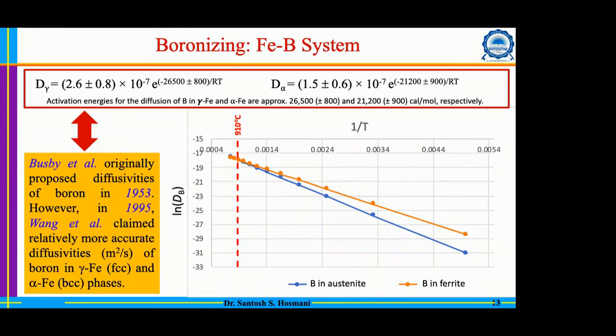And in 1995, the equation which is mentioned on the screen was proposed, and people still use this particular expression. What is important to notice here is that as the temperature increases, especially beyond 600 degrees Celsius, diffusivity is not really much different in the ferrite matrix as well as the austenite matrix. So in principle, unlike the carburizing process, there is no requirement that you need to be in the austenitic phase region.